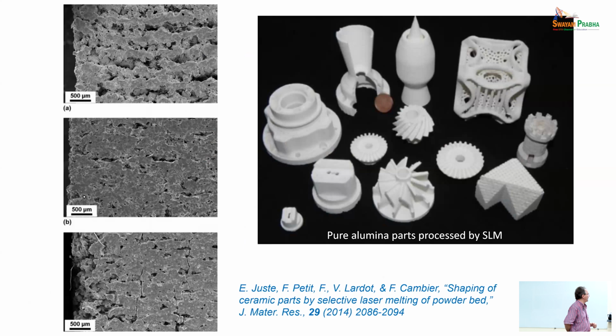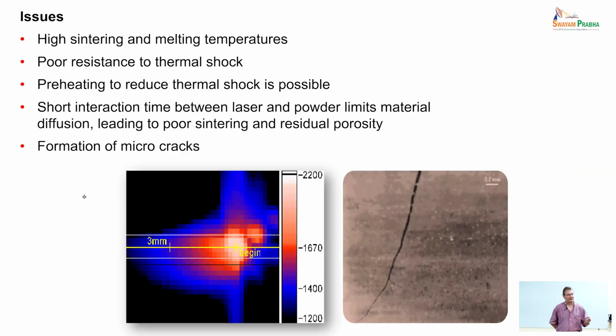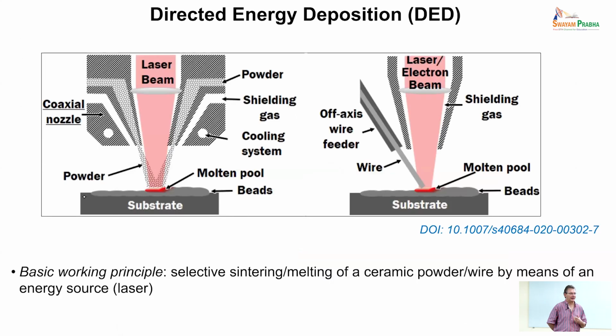And this is due to the fact that you have very high temperatures, fast heating, and more importantly, fast localized cooling. For ceramics, this leads to cracking because not all ceramics are very good in terms of thermal shock resistance. So I'm not familiar with any large-scale application of this technology for ceramics, while for the other technologies that I've described, there are a lot of examples. Directed energy deposition works well with metals.